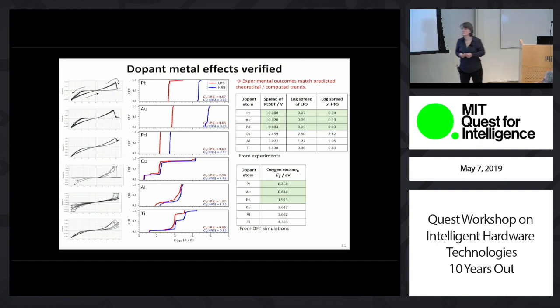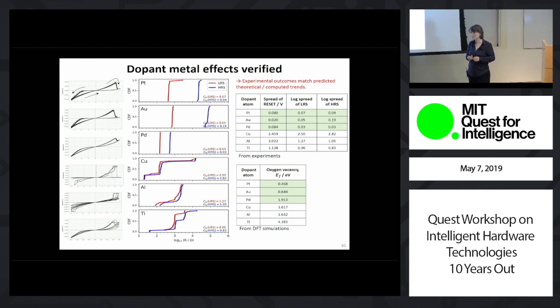Bilge? Yes. Thanks. Very nice talk, Bilge. Thank you. What is the effect of this dopant implantation on the electroforming, for instance? They don't need electroforming. Okay, but before the implantation? Then you need electroforming. Okay, so with this strategy also you cancel the electroforming? Yes. And you also obtain multi-states switching with a very smooth change in the set range that I did not show given the time, but it's a really nice system.